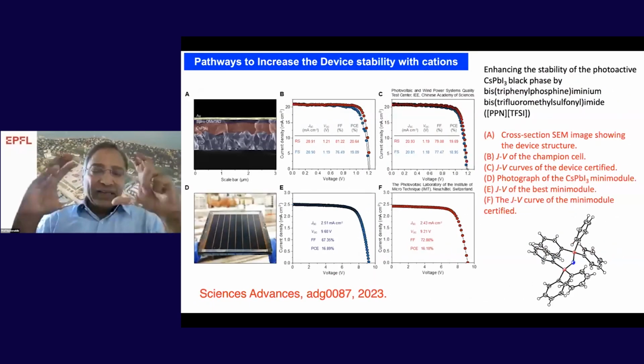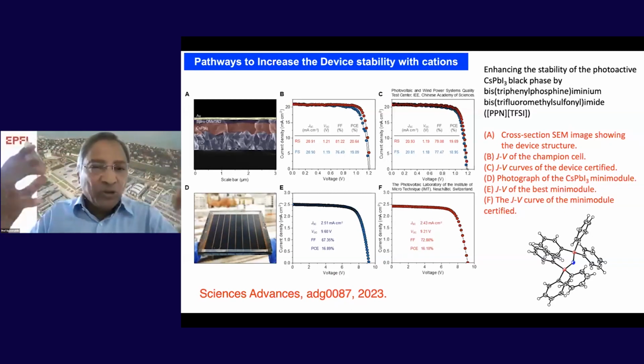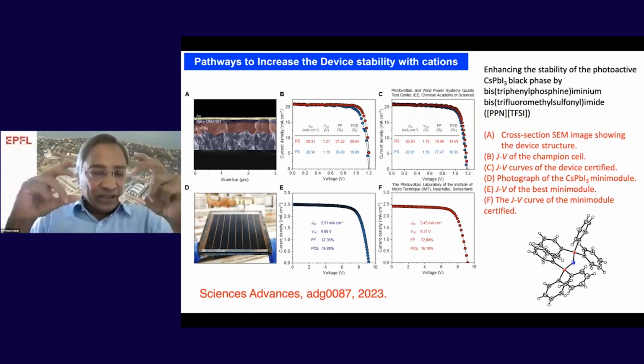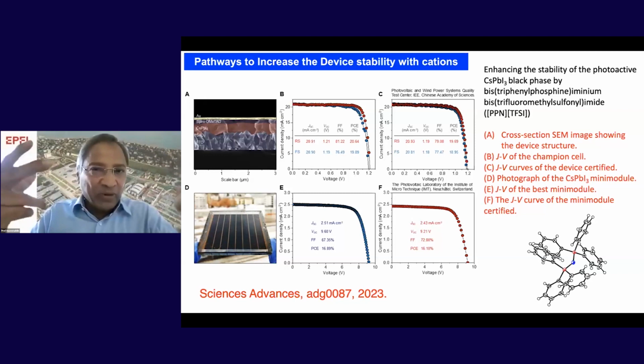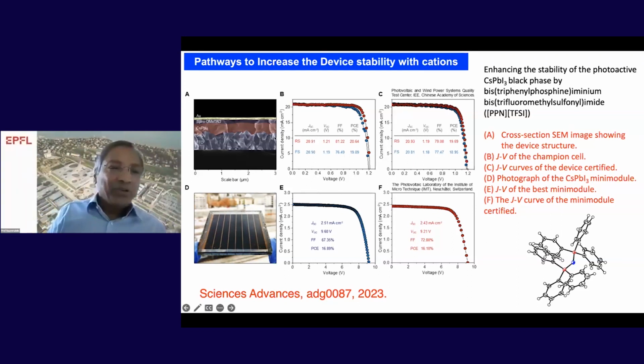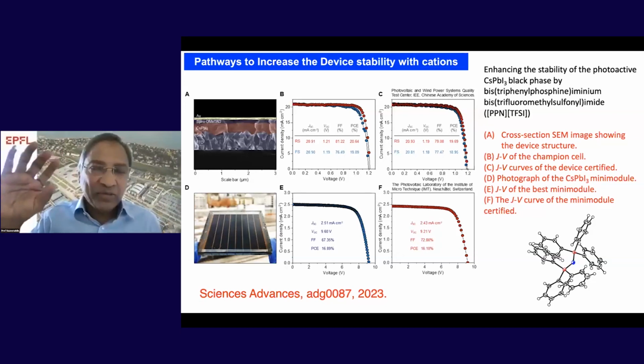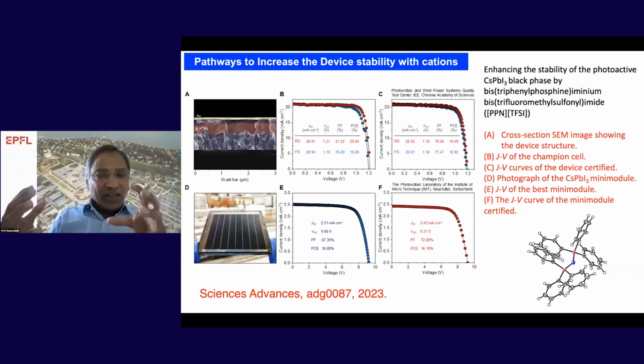If you look at the organic cations, they have issues. For methyl ammonium, sublimation, the dissociation, is the biggest problem. Formamidinium has alpha and delta phase transformation. Also, for the tandem configuration, the optimum band gap of the perovskite should be around 1.7 eV. You can obtain 1.7 eV by replacing the organic cations with a cesium cation. So here is the cesium cation containing perovskite. However, the problem with cesium lead iodide perovskite is the stability of the alpha phase, the black phase, which also undergoes transition into a delta phase, the yellow phase. But here the question is, how can you stabilize the alpha phase of cesium lead iodide perovskite?